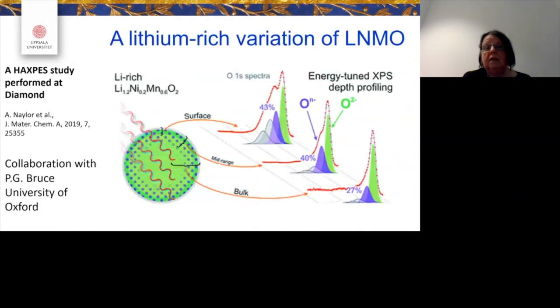So my second example is a lithium-rich variation of this LNMO. And here we used HAXPES, which means that you can tune your photon energy to get to the surface and then deeper and deeper in. This is done, in this case, at Diamond in the UK. Normally we go to Berlin to do these things. And again, it was more trying to see, can we understand this kind of anion redox reaction that people start to believe exists?